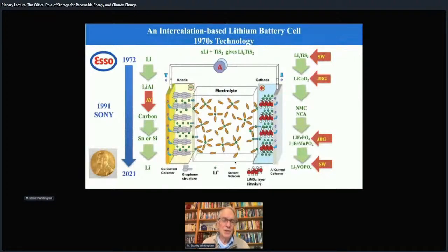But before I get into the challenges and opportunities, let me very briefly mention what a lithium battery is and what it isn't. So lithium batteries are based on intercalation. What we mean by that, if you look at the little green ions here, they are inserted within the crystalline lattice. In the case of the anode, it's graphite. In the case of the cathode, it's normally a layered compound. Originally, this was TiS2. It's now a range of materials, but particularly oxides. So the lithium ions go in and out of these materials. So they shuttle when fully charged in the anode. They move through the electrolyte into the cathode. And I'll show you in a moment why we do not have any lithium metal in these batteries.